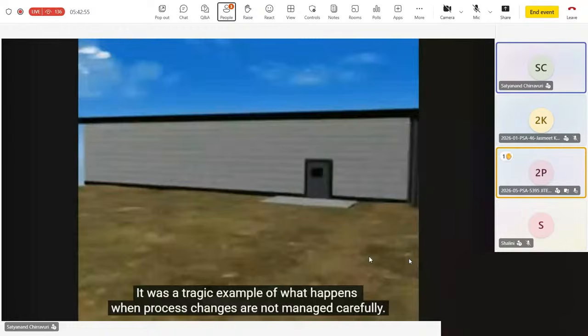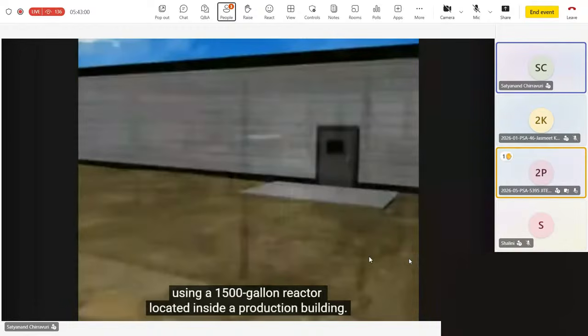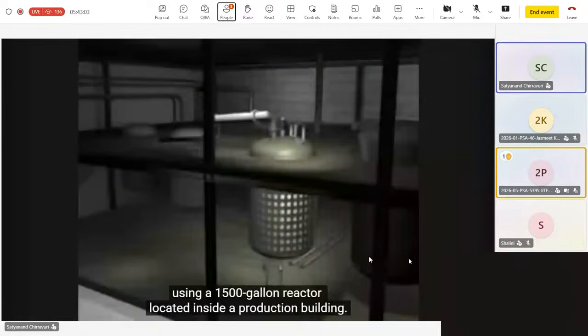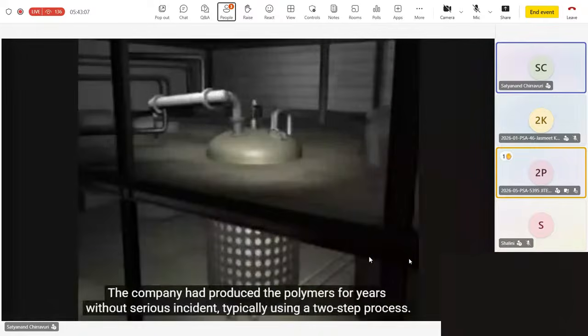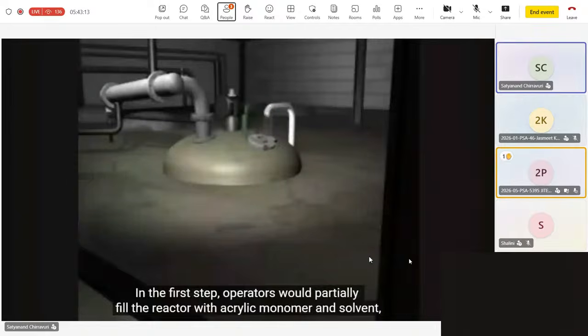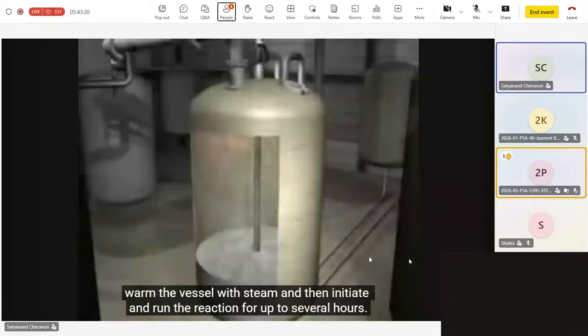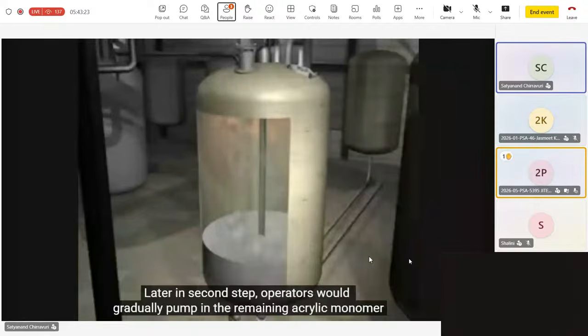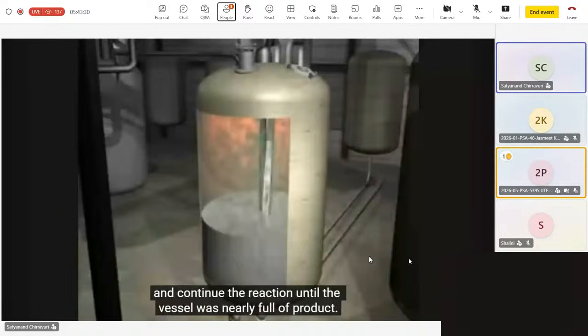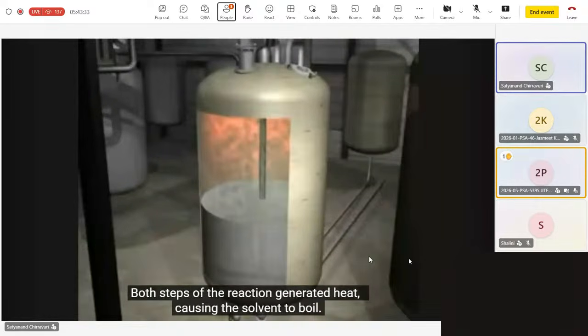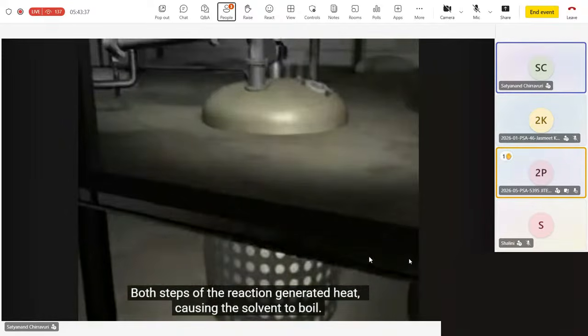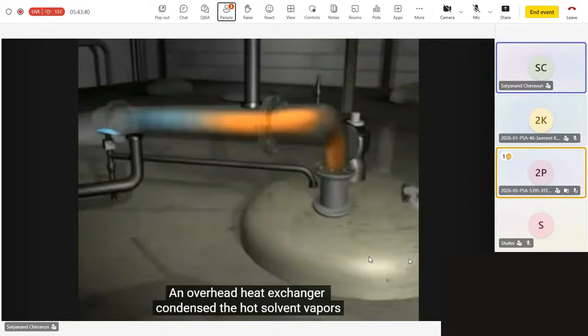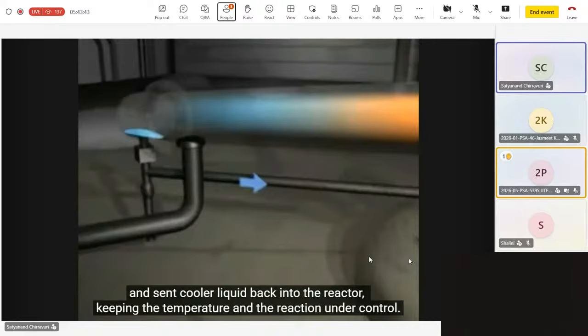Synthron manufactured acrylic polymer coating additives in batches using a 1,500-gallon reactor located inside a production building. The company had produced the polymers for years without serious incident, typically using a two-step process. In the first step, operators would partially fill the reactor with acrylic monomer and solvent, warm the vessel with steam, and then initiate and run the reaction for up to several hours. Later, in a second step, operators would gradually pump in the remaining acrylic monomer and continue the reaction until the vessel was nearly full of product. Both steps of the reaction generated heat, causing the solvent to boil. An overhead heat exchanger condensed the hot solvent vapors and sent cooler liquid back to the reactor, keeping the temperature and the reaction under control.